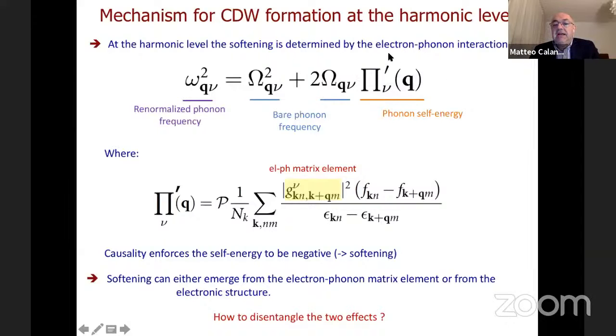And this correction is related to Pi prime, the real part of the phonon self-energy, that has this shape with f the Fermi functions evaluated at epsilon_kn, epsilon_k+qm, and these are the band structure. And this is the electron-phonon matrix element that tells you how the electronic structure reacts when you displace an atom. Now, due to causality, Pi prime is negative. So the correction to omega squared, to capital Omega squared, is always negative. And so the electron-phonon coupling tends to soften the phonon frequency and push it down.